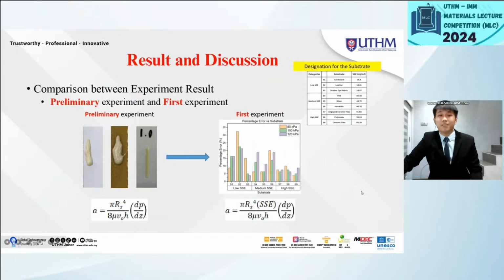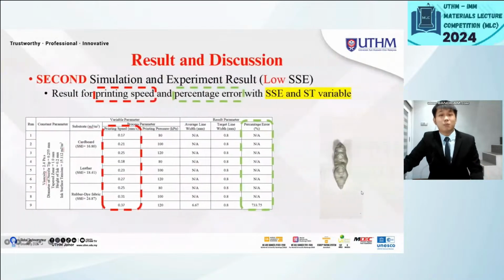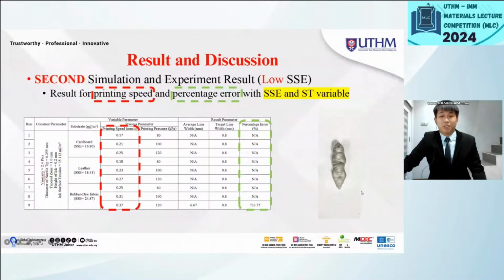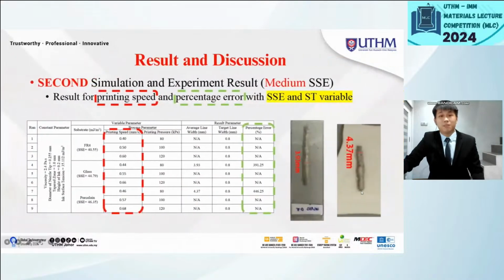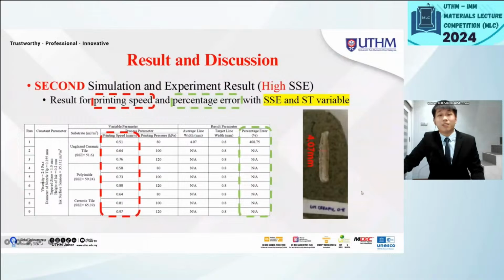Here are the tables showing the experimental results for low, medium, and high substrate surface energy conditions for second simulations and experiments, with integrating substrate surface energy and ink surface tensions into existing models. The table presents the printing speeds and the corresponding percentage error for each substrate surface energy level.